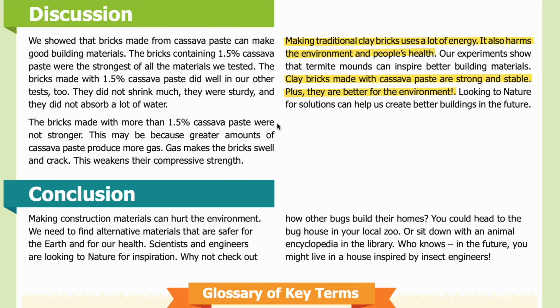The bricks made with more than 1.5% cassava paste were not stronger. This may be because greater amounts of cassava paste produce more gas. Gas makes the bricks swell and crack. This weakens their compressive strength. Making traditional clay bricks uses a lot of energy. It also harms the environment and people's health.